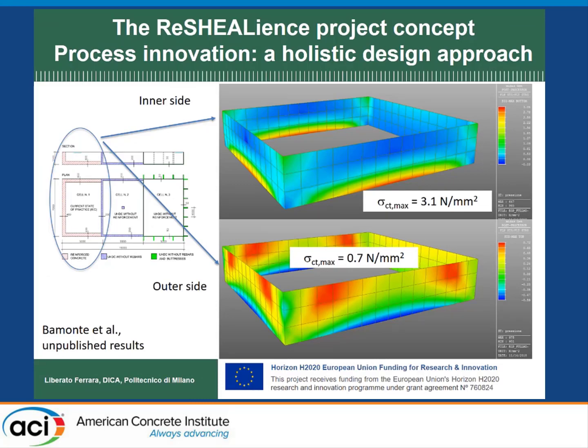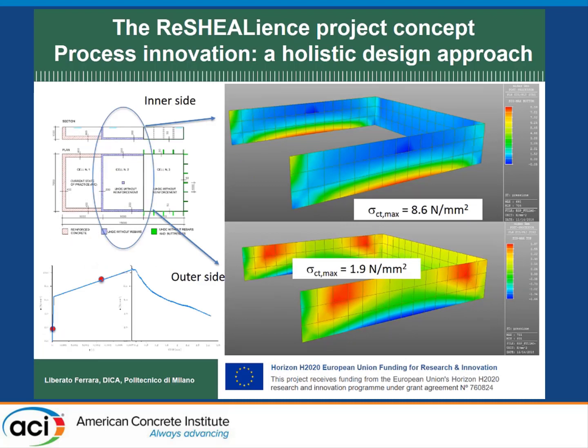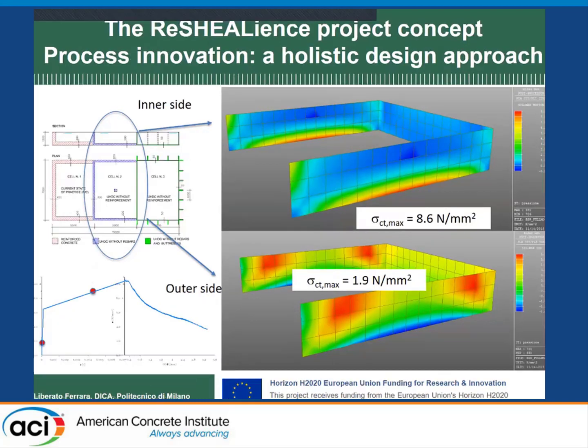Then we designed two alternative structural concepts, only with UHPC, with no ordinary reinforcement. This is a 6 centimeter thick, only UHPC structure, and you can see the expected tensile stresses from a finite element analysis. If you compare the design stress-strain and stress-crack opening law, you can see the red dots are where these stress levels are on that constitutive relationship. So we are in the strain hardening regime and well below the strain hardening capacity of the material.